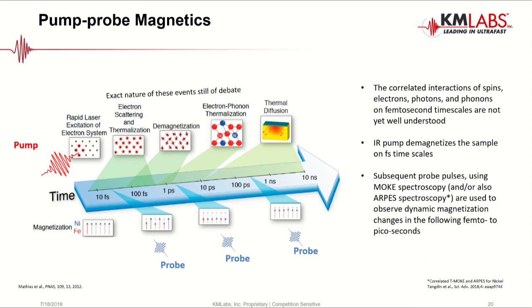And we can start to understand them using this pump probe methodology, where we can use a probe beam that will give us sensitivity to spin states in particular elements. And that's what's shown on the bottom here, where we're looking at the magnetic spin states of, in this case, nickel and iron, shown by the blue and red arrows. And we can probe those at different time delays to watch how those spin states change over time. And we're actually doing this as sort of a side comment here.